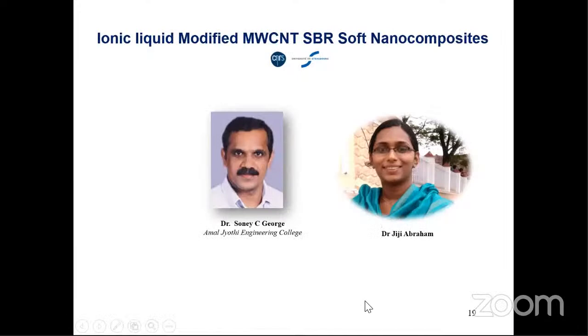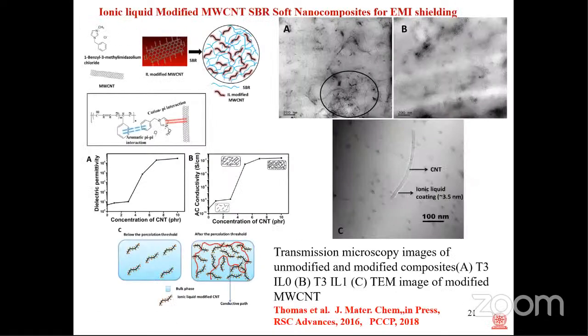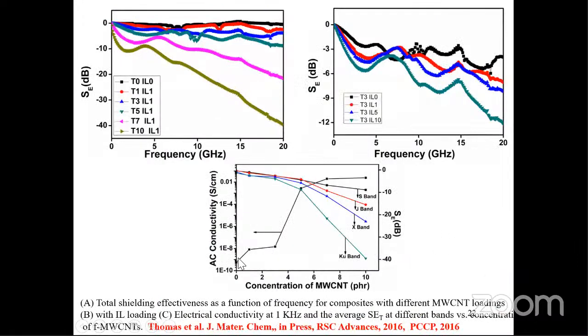Let me show you some of our work on multi-wall carbon nanotube. You can see our collaborators and PhD students. We put multi-wall carbon nanotube into rubber. We also used a beautiful coupling agent, ionic liquid. This is the ionic liquid. Ionic liquid can connect SBR rubber and carbon nanotube. When we use ionic liquid, you see carbon nanotube is beautifully dispersed in the polymer matrix. If you don't use any ionic liquid, you have lots of agglomeration. Look at this. You can see this type of percolation we got.